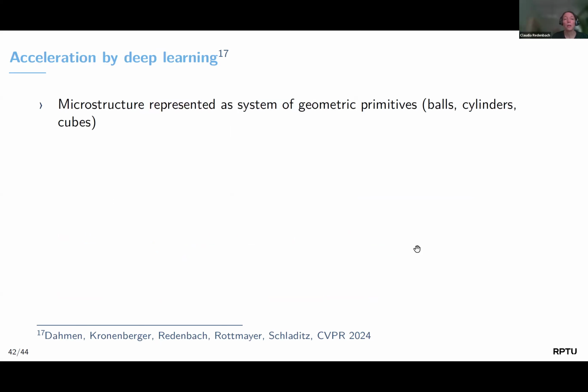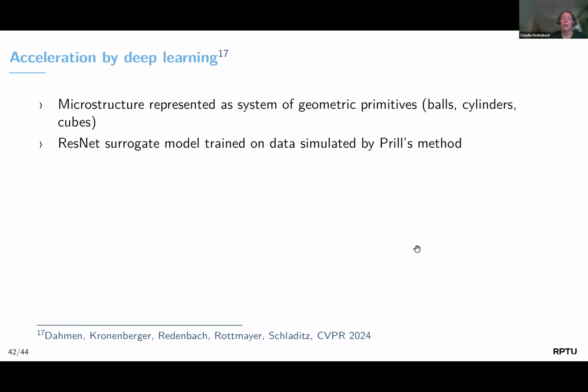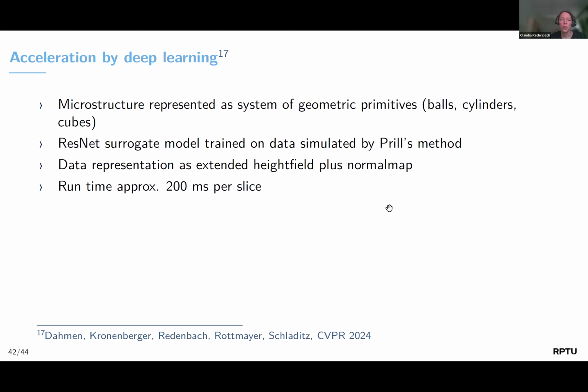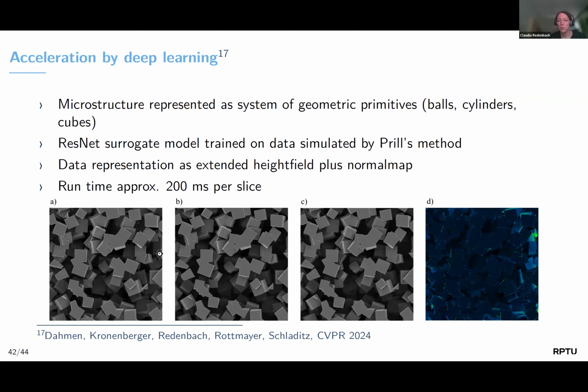So therefore, we worked on a deep learning acceleration. So the idea is you have a microstructure represented by balls, cylinders, or cubes. And then we have a ResNet surrogate model that is trained on data simulated by Prill's method. The main point here was to get a nice representation of the microstructure. So here height fields and normal maps turned out to be very useful. And this way we can simulate a single slice in 200 milliseconds. And here you see some examples.